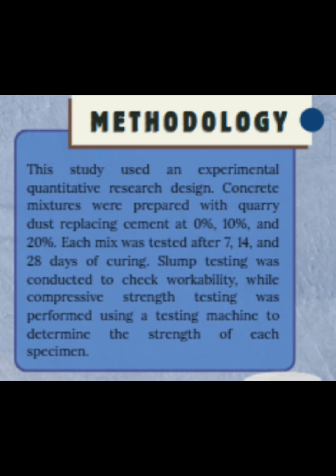Our study followed an experimental quantitative research design. First, the materials were gathered and prepared. Concrete specimens were then produced using quarry dust replacement levels of 0%, 10%, and 20%. The specimens were cast in cylindrical PVC molds and allowed to cure. Compressive strength tests were conducted after 7, 14, and 28 days of curing using a compression testing machine. This allowed us to evaluate how different percentages of quarry dust affected the strength development of concrete over time.